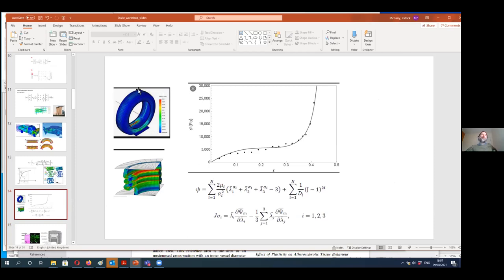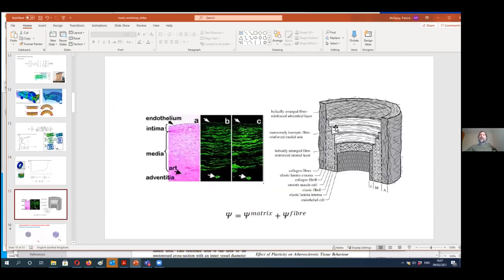In other words, the material doesn't really have an aligned microstructure. Every direction in the microstructure is similar, but that's not the case for this artery. If I stretch it in the radial direction and this direction here, I'm getting a very different response to if I try and expand its circumference. So the kind of deformation that I do on an artery will determine its behavior.